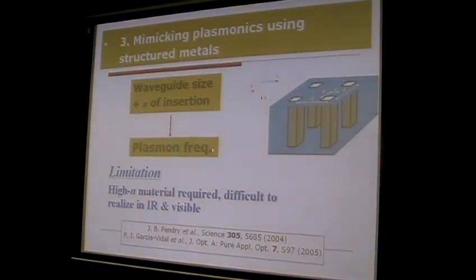And also, there's some recent idea. For example, in 2004, John Pendry proposed a structure and found that for this kind of structure, if you insert a very high index material inside the waveguide, inside this square-like waveguide, you can mimic the surface plasmon properties. The limitation is that you have to insert some kind of high index materials. The high index material is not so easy to realize, especially at high frequency.